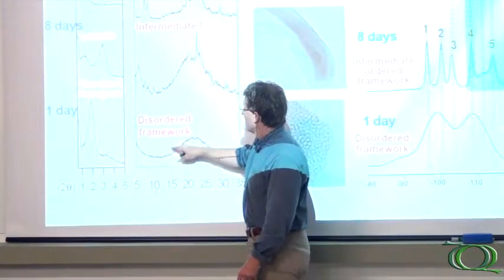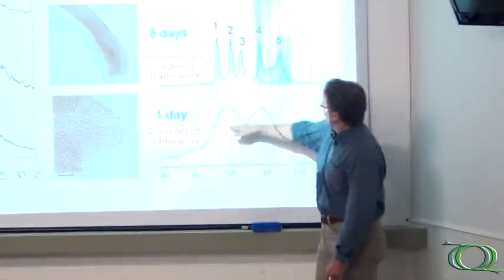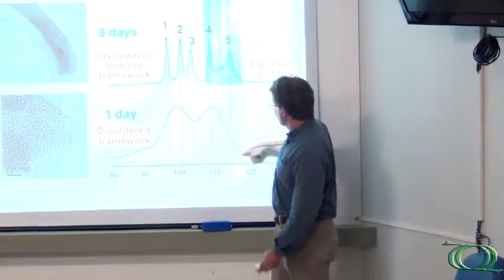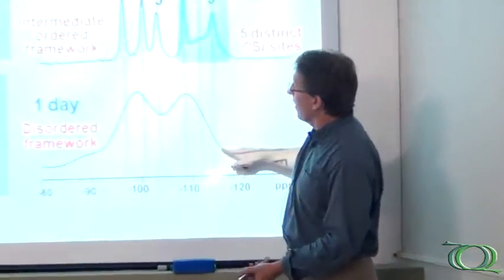No sign of high angle scattering, so this is a relatively poorly ordered framework that corresponds with this silicon NMR where you have a very broad distribution of sites which reflects a glass-like environment. This is an amorphous or disordered framework with some loose structural ordering.